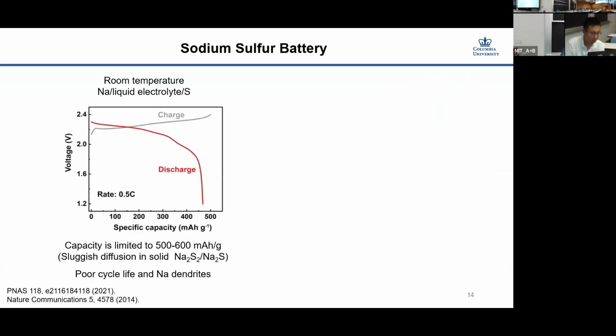To address these issues, people have looked at the low temperature sodium sulfur battery, where you basically use a liquid electrolyte, a sodium metal solid anode and a sulfur cathode. So they have similar problems to the lithium sulfur battery with electrolyte at room temperature, and the capacity is also limited by the low utilization because the kinetics in the solid sodium disulfide and sodium sulfide are pretty bad.